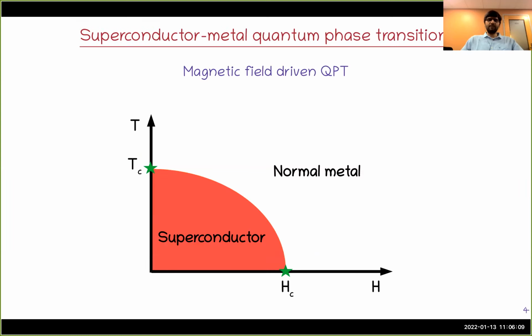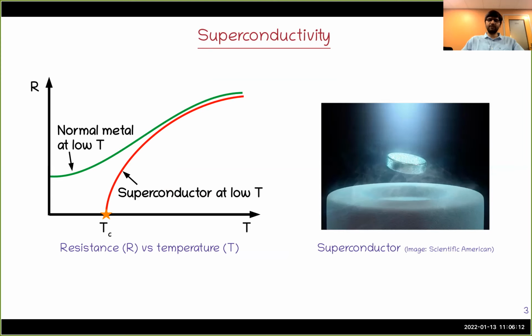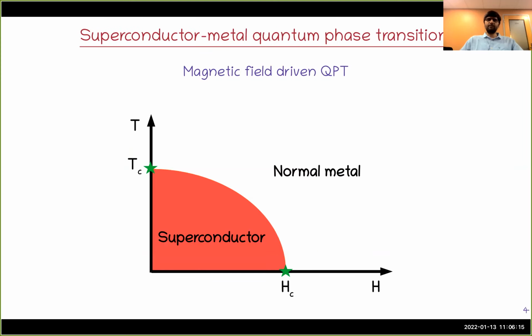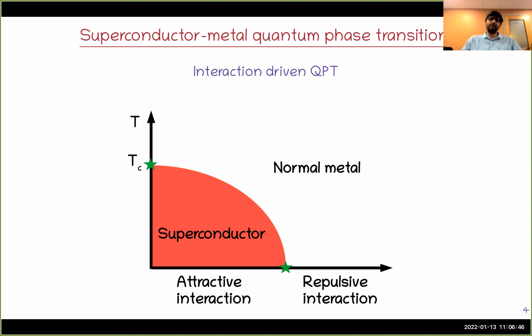Apart from just this thermal phase transition, which is as a function of temperature, you can also have a quantum phase transition, meaning a T equals 0 phase transition, which is not driven by temperature but by, let's say, a magnetic field. Schematically, you have temperature on the y-axis and magnetic field on the x-axis, and you have some superconducting material. This superconducting phase could be destroyed if you increase temperature and go above Tc, or at T equals 0, you can increase the magnetic field beyond some critical value and become, again, a normal metal. Similarly, you can also have some interaction-driven superconductor to normal metal phase transition.